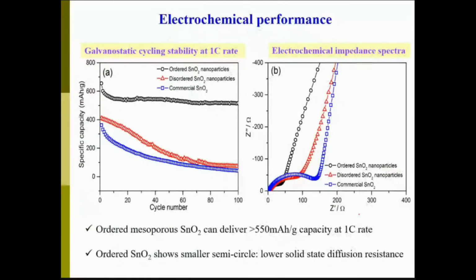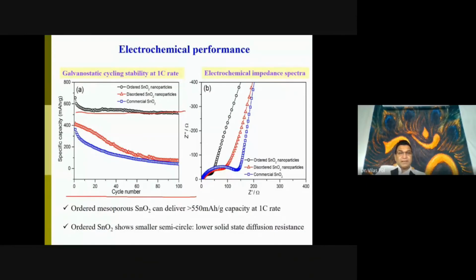What you are seeing here is the electrochemical performance. In the previous titania case, you were seeing around 200 milliamp hour per gram capacity. Here the capacity is almost 3 times higher, around 500 milliamp hour per gram, and this battery cycles for a long time. If you do not have the architecture made, then the battery dies much faster. Even the commercial material, which is very expensive to get, did not work very well. The capacity is close to 0 in 100 cycles. That means within 100 days, with daily charging and discharging, the battery is dead.